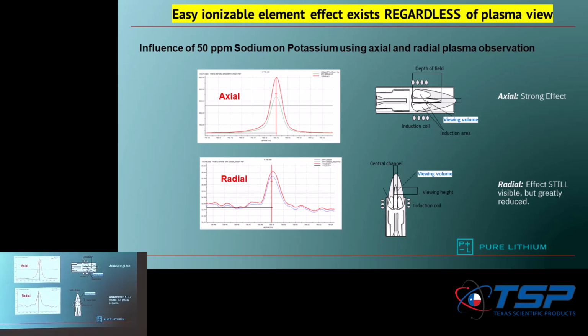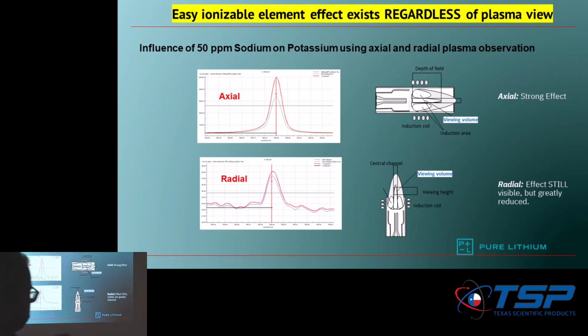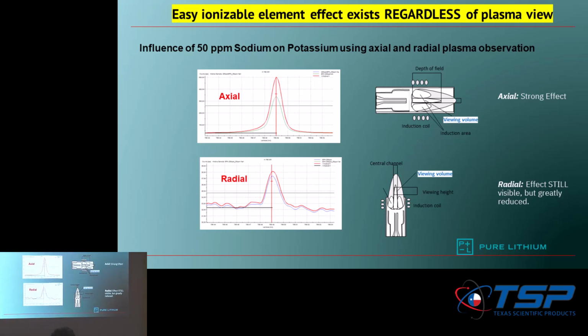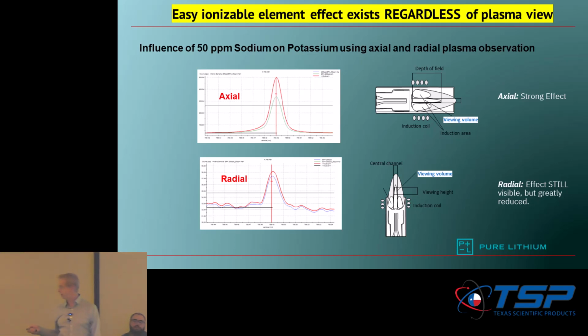And mine does not. It's a research environment, so I have no idea what's coming through that door at any point in time. So please keep that in mind, that even though this is a much easier way to handle, you're going to get better linearity and there's going to be less issue. If you pump enough sodium in there, if you start talking sodium at % levels, and then you're looking at trace lithium or potassium, you're going to see the same effect on a radial system.